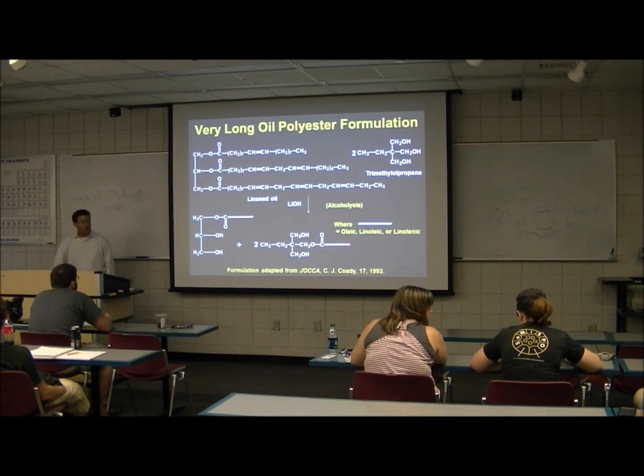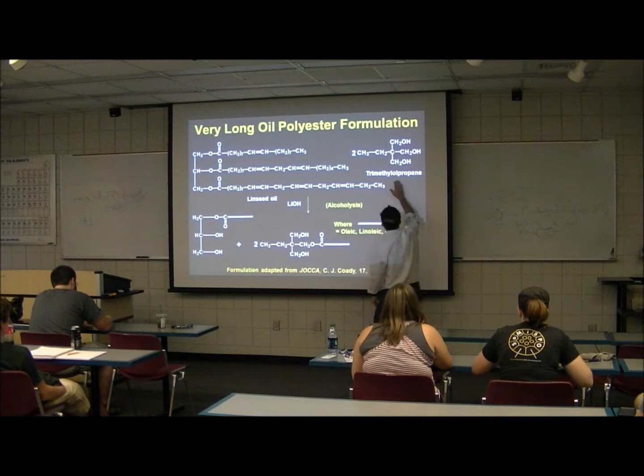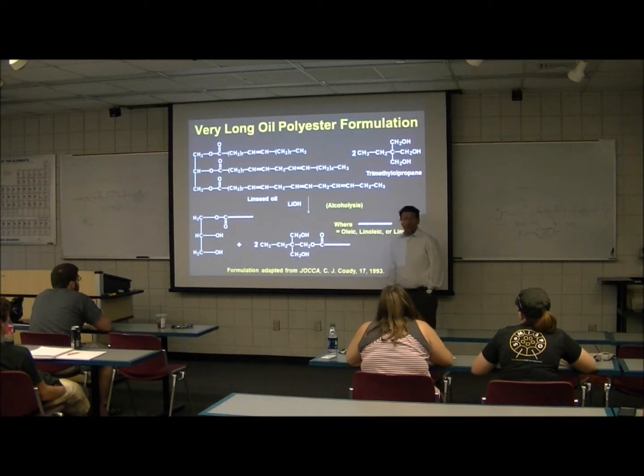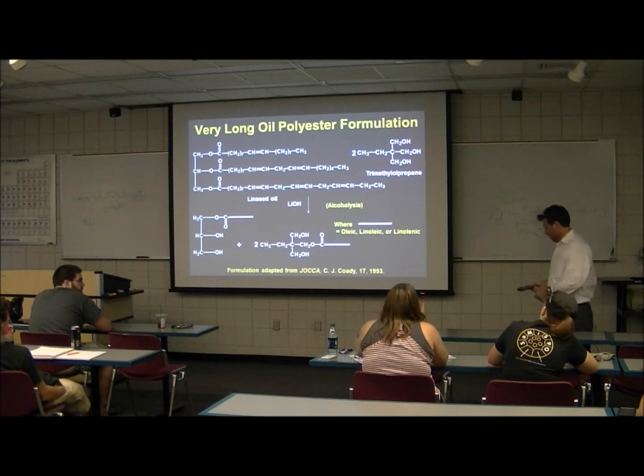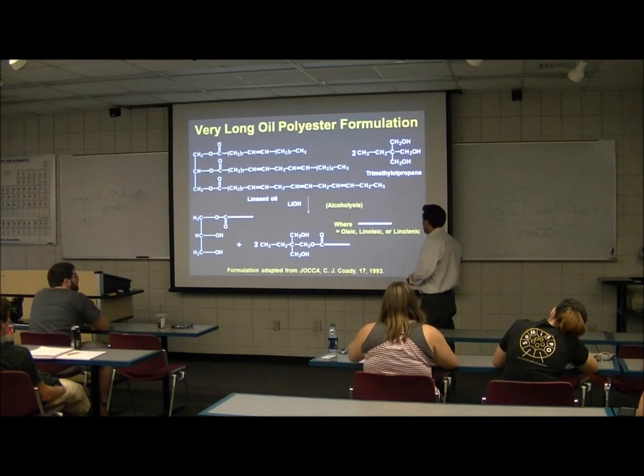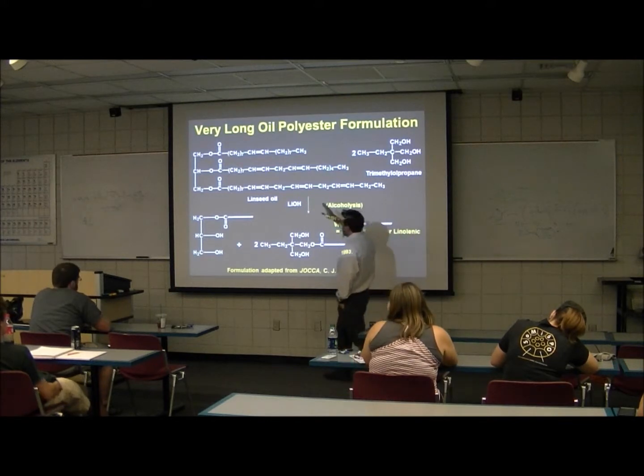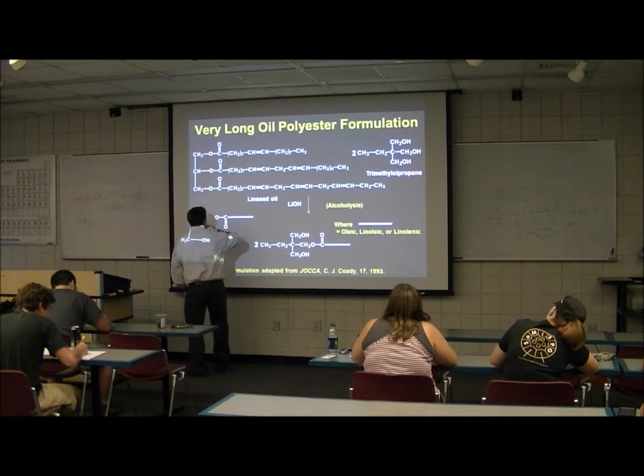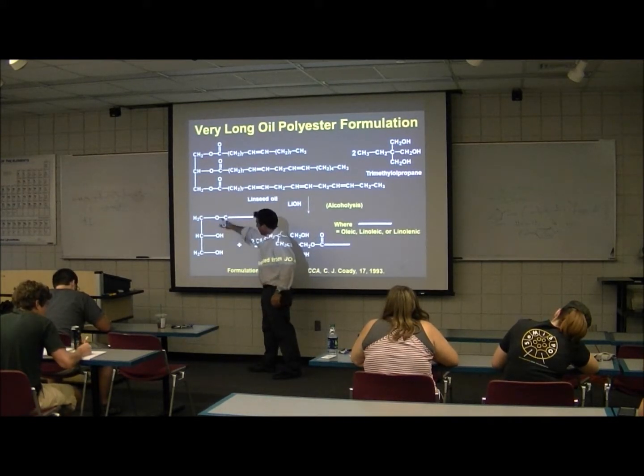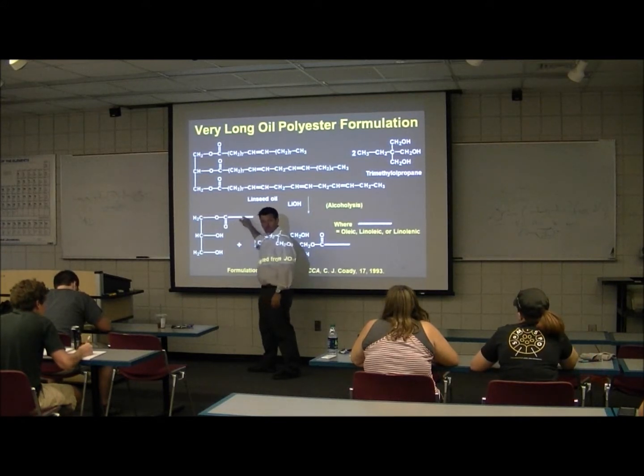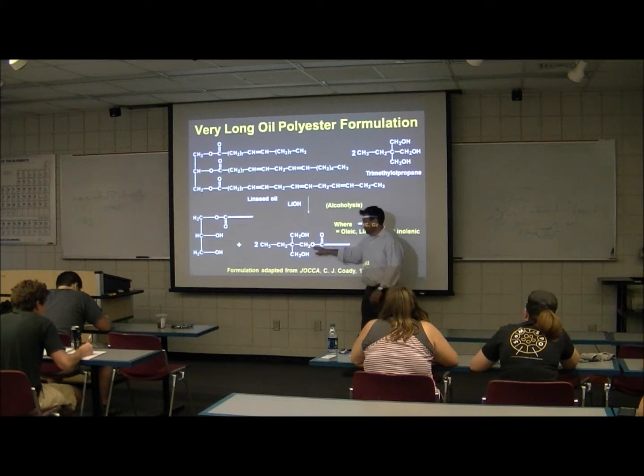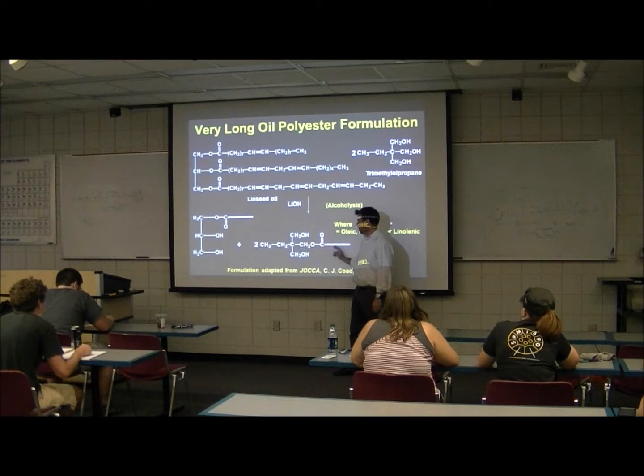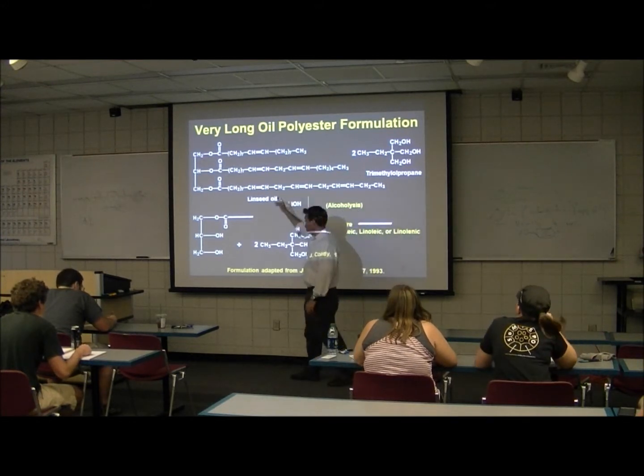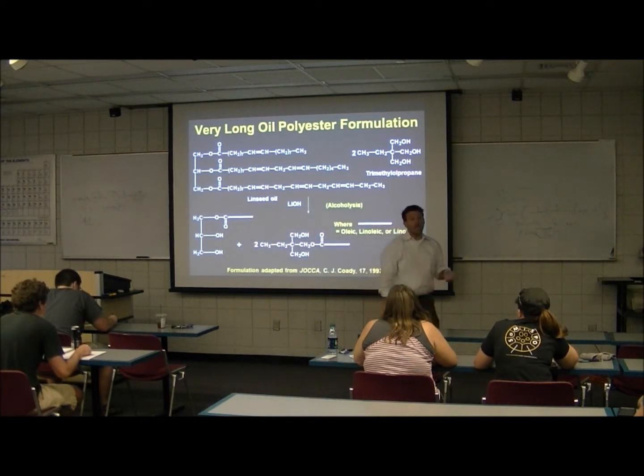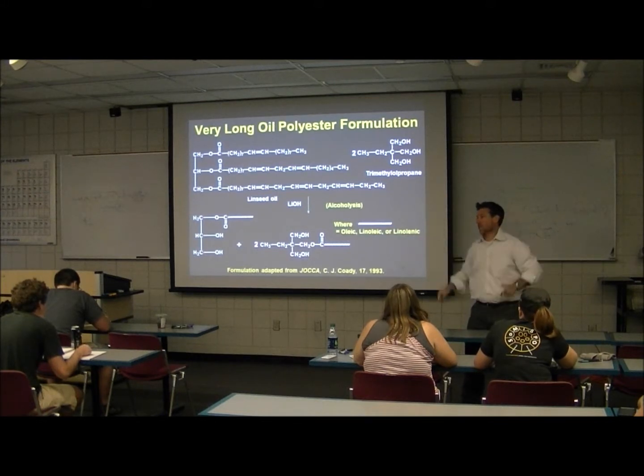So here we go. Let's step back. Here's linseed oil, lithium hydroxide, trimethylolpropane. This first step is called alcoholysis. Alcoholysis is pretty important in that this is how we break these esters and rearrange so that we have a structure that looks like this, which we would call the monoglyceride. One ester in the glycerol molecule, and that makes this an AA monomer. But we also have two of these monoglycerides, but they're really not glycerol. But it'd be the mono substituted. So at a 2-to-1 ratio, we end up with 3 monoglycerides, or 3 AA monomers, to grow linearly with some branched side chains that are fatty acids.